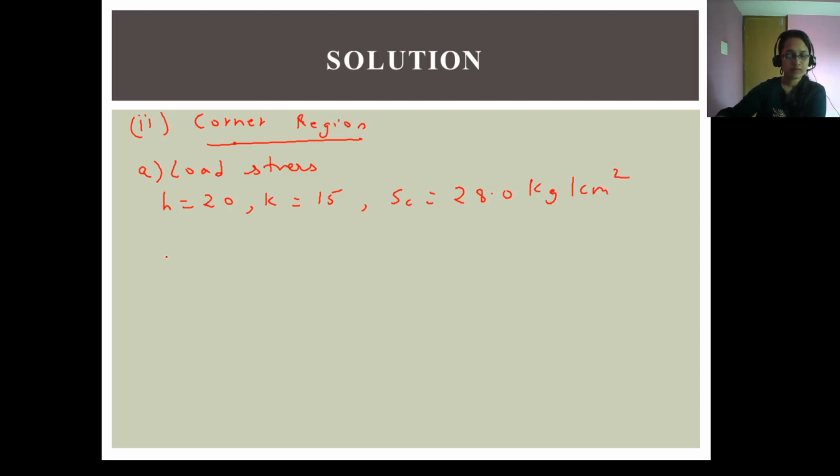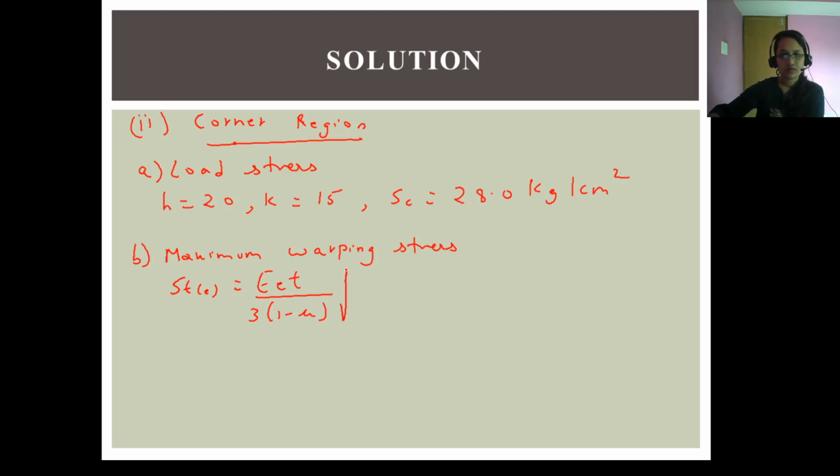Now for the maximum warping stress, that is B. That is S_te, which is E small e t upon 3(1 minus nu) times square root of a upon l. Substitute all this in this equation.